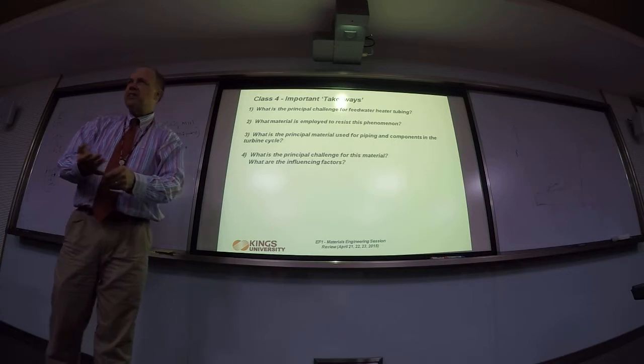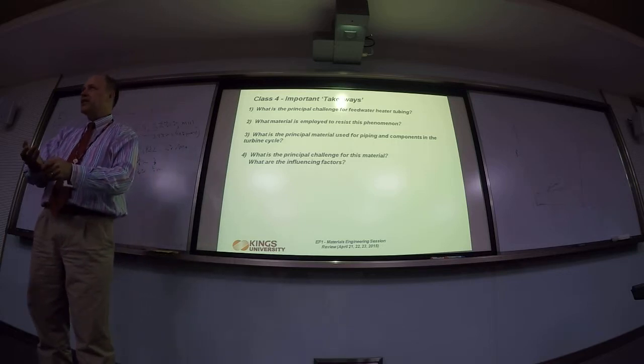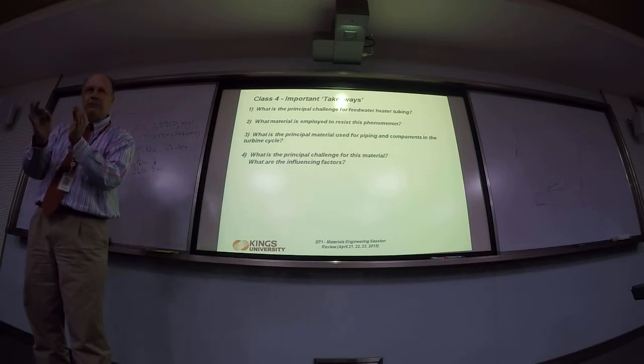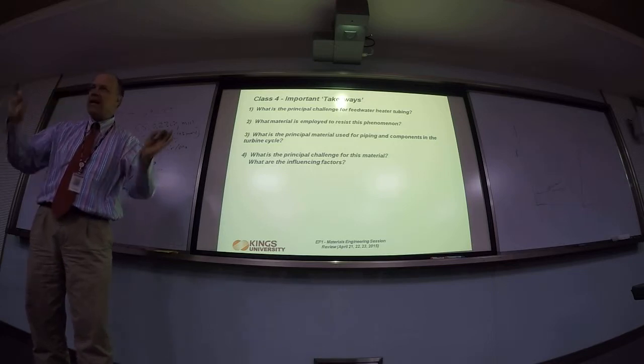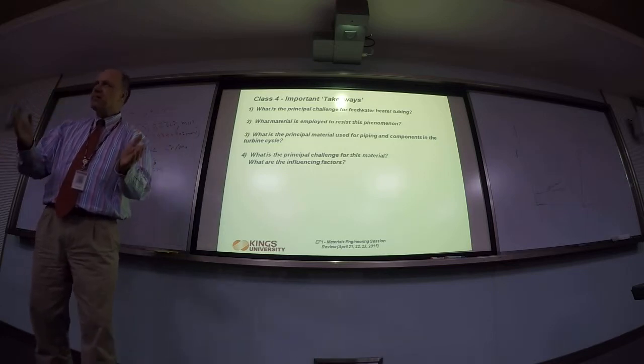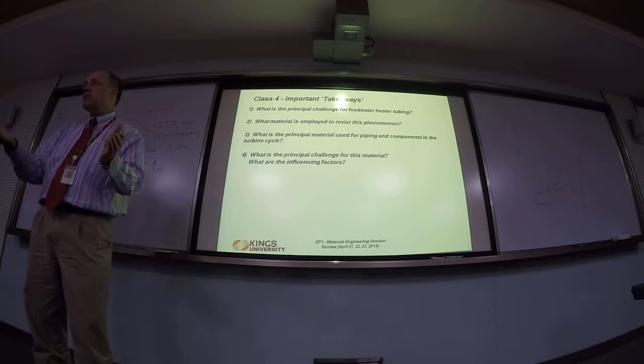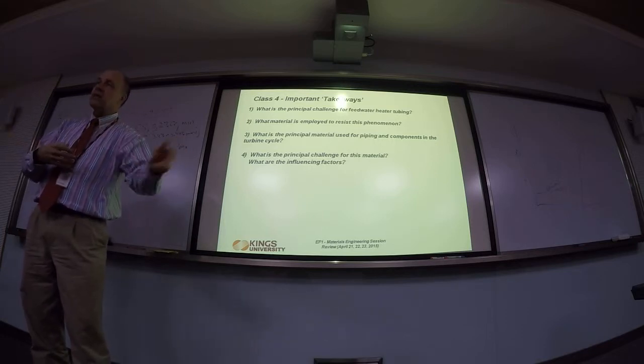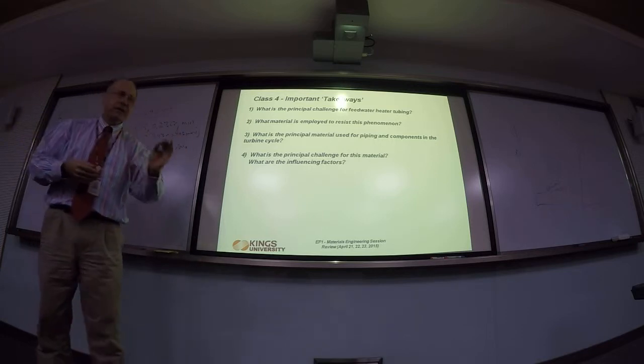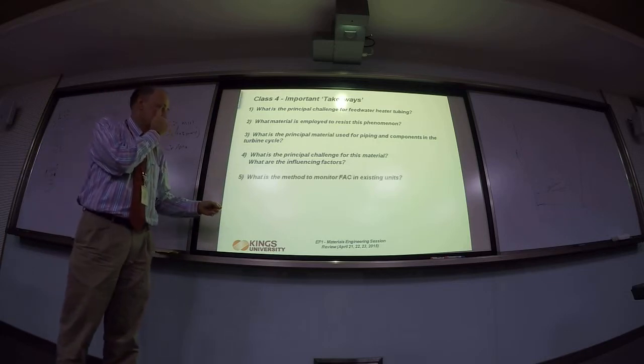How much oxygen is good? No oxygen? You need a little bit. If you take all the oxygen away, FAC is really bad. You need a little bit. Too much oxygen, you have general corrosion attack. Too little oxygen, you have too much FAC. You need a little bit of oxygen, right?